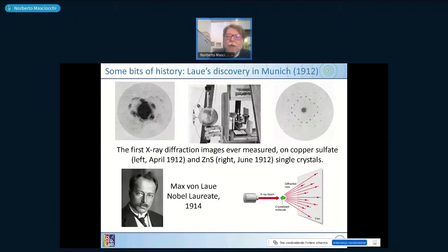Now we go back 20 years, from the 1930s we go to 1912. In the first panel left, you see a few spots like the dirty fingerprints, and this was the first diffraction image ever measured by Max von Laue and his students. And he learned that these spots were not random and then could be optimized by using a better experiment. And just a few months later, 2 months later, a different material, zinc sulfide, was exposed to X-rays and gave very nice tiny spots, ordered and symmetrically arranged.